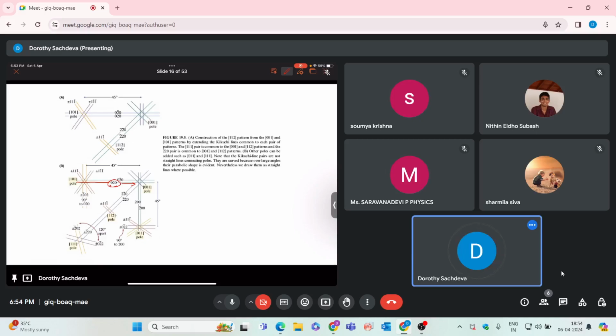So how will you know that you are following the 020 line? You will know by experience, because the thickness of the lines tells you whether the family of planes is different or not. And similarly, if you want to go from the 001 zone axis to the 011 zone axis, then you need to follow again 200, because this 200 plane is common in the 001 zone axis as well as in the 011 zone axis. This is the common plane, so you need to follow this plane because it will exist in both zone axes.